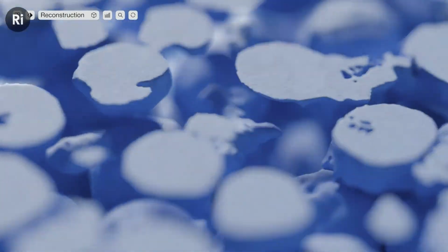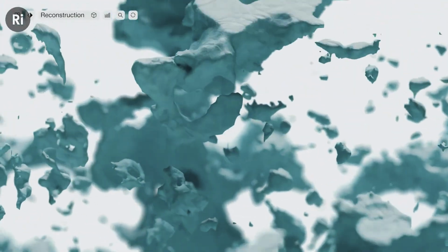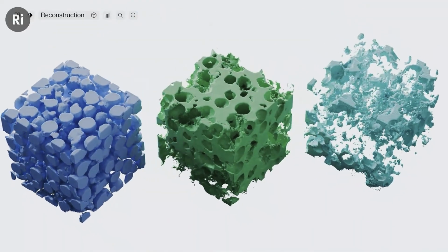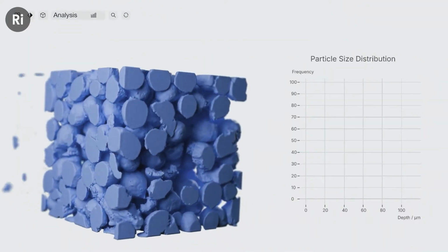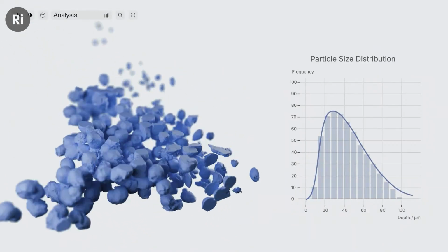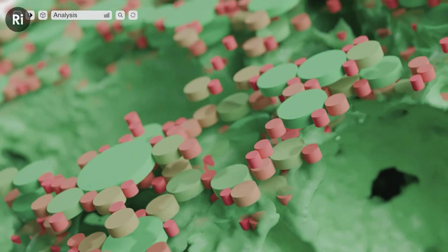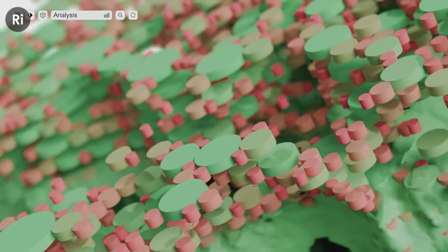We need to understand the distribution of particle sizes, the connection of interfaces, the tortuosity of pore networks, and the electronic transport through the solids. These are 3D concepts. However, 4 years ago, a brilliant student of mine, Steve Kench, discovered a method using generative AI to generate 3D structures from a single 2D image. This means that you can speed up your characterization workflows by a factor of 100 and extract all the complicated battery-relevant metrics from a single two-dimensional image.